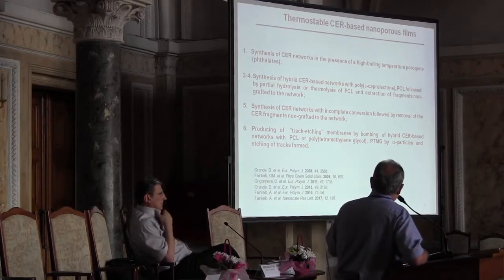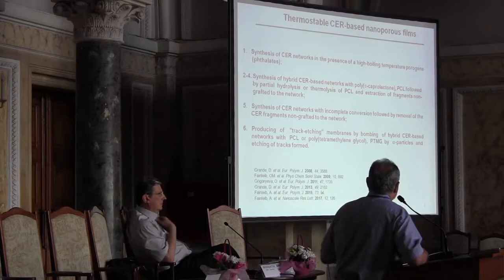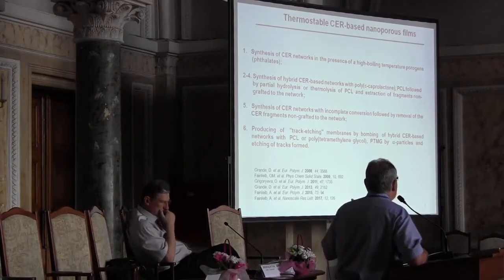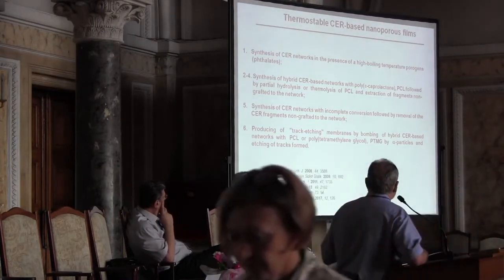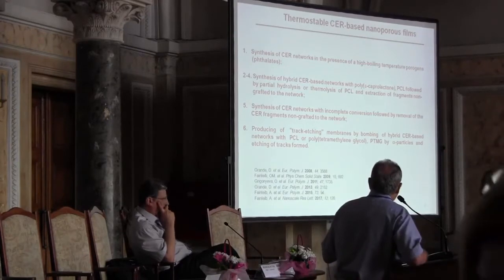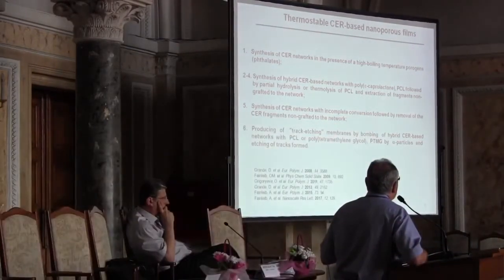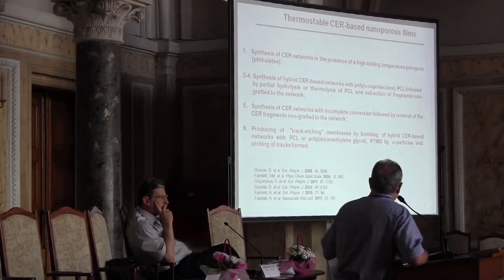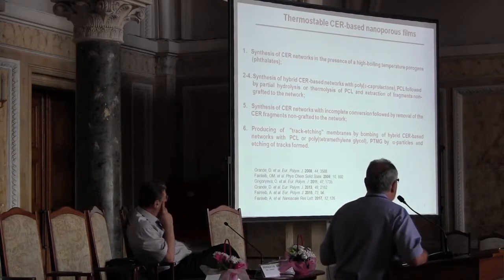Then from number 2 to number 4, synthesis of hybrid cyanate ester-based networks with poly-epsilon-caprolactone, followed by partial hydrolysis or thermolysis of PCL and extraction of fragments non-grafted to the network. Number 5 is synthesis of cyanate ester networks with incomplete conversion, followed by removal of the fragments non-grafted to the network. And final number 6, producing track-etching membranes by bombing of hybrid cyanate ester-based networks with PCL or polytetramethylene glycol by alpha particles and etching of tracks formed.